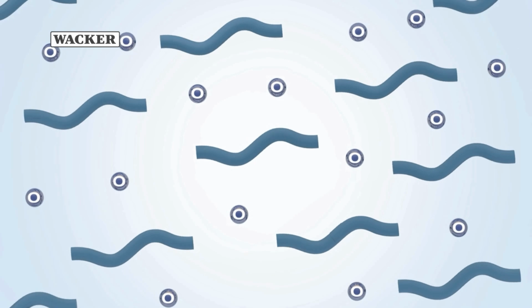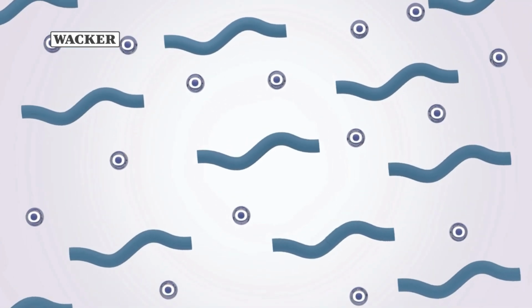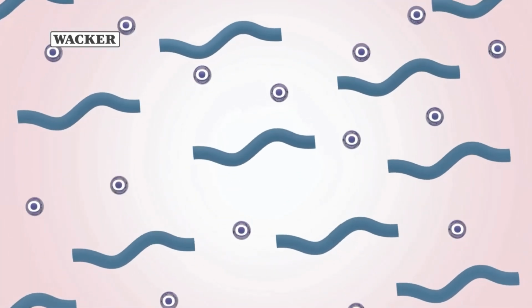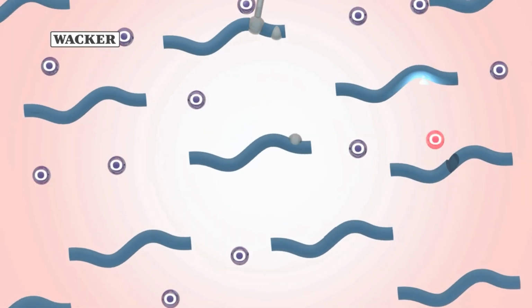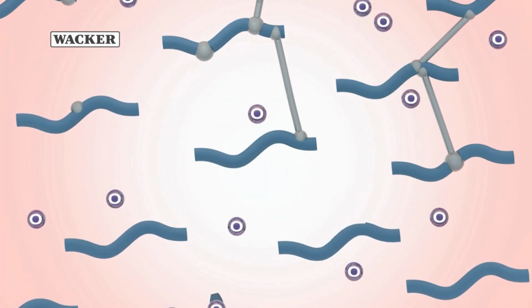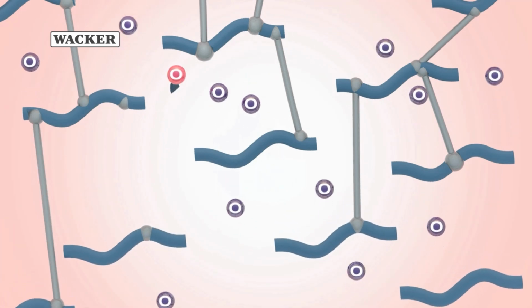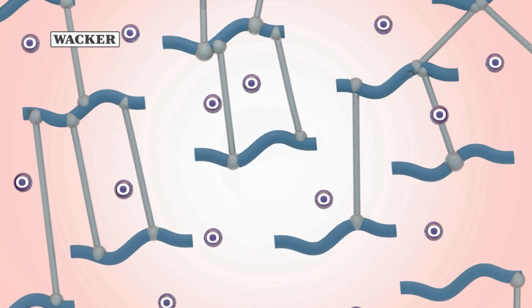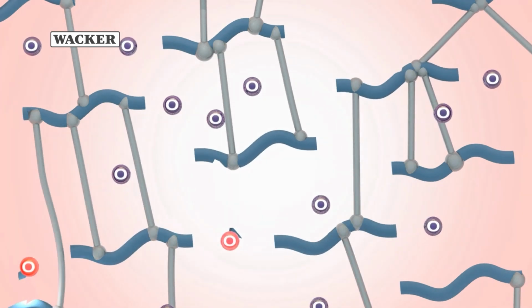Silicone fluids consist of polymer chains. When the product is heated to temperatures of over 170 degrees Celsius, many of these chains are damaged by oxygen molecules. The damaged polymers then react at precisely these points to produce a three-dimensional network. The first sign of this is an increase in viscosity. When degradation is complete, a gel or rubbery material is produced.